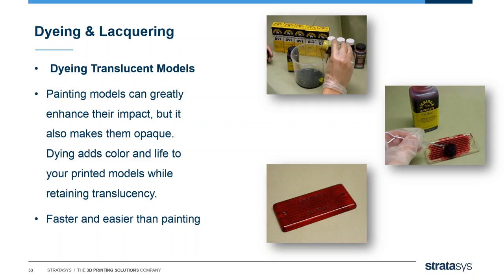So what makes sense? It makes sense if you want to have polished and dye colored parts: color or polish your parts first and then start the dye coloring. Of course, you should not use any lacquer here to make the parts more transparent, because a lacquer is closing the porosity and you will have no effect with a dye coloring.